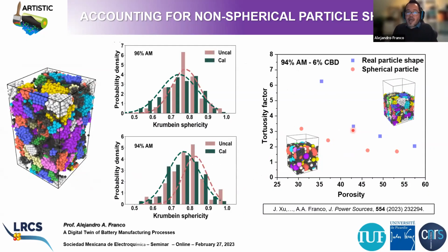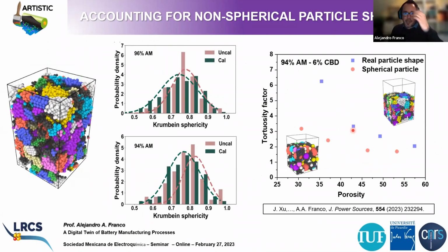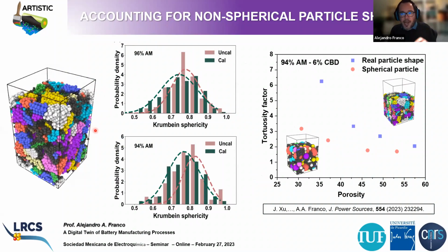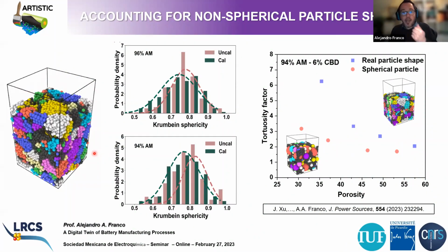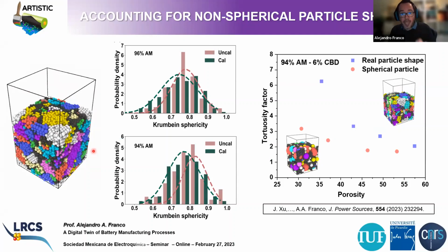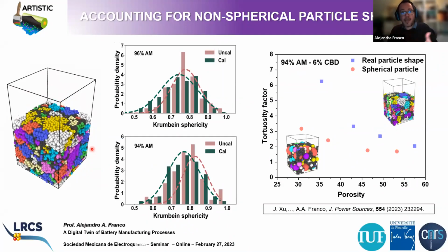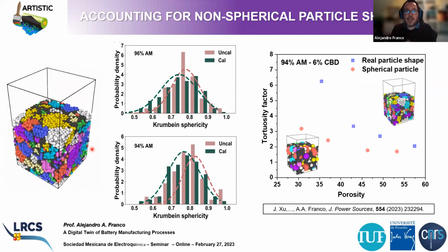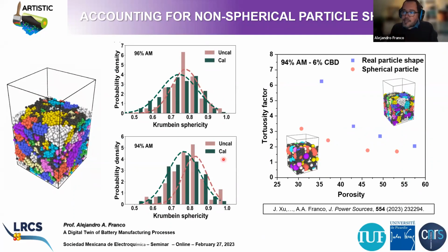And here I'm going to show you a couple of examples of what you can get with these more sophisticated models. So for instance, you can predict the influence of calendaring on the electrode microstructure, and you can account for the deformability, the deformation of the active material particles because of the calendaring process parameters, right? The compression degree, the temperature, and so on. Here you see some quantifications of this deformability. This is the Krumbein sphericity, the probability density as a function of the sphericity. When you calendar electrodes, the particles are becoming less spherical, right? They are getting deformed, right?